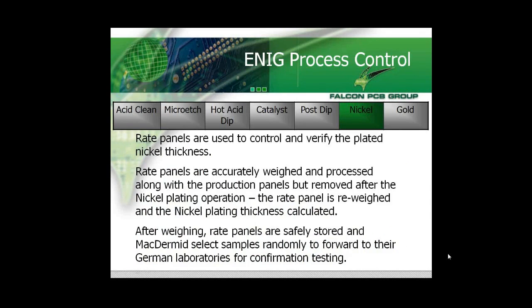What we use are rate panels to control and verify the plating thickness. Rate panels are accurately profiled pieces of laminate where we etch off the copper, so they're just base laminate, and we process them down the line with a jig or fixture full of normal production panels. What we do after the nickel plating operation is we remove those rate panels and we weigh them. The weight of the panel initially, obviously, we subtract from the rate panel weight and we calculate the nickel